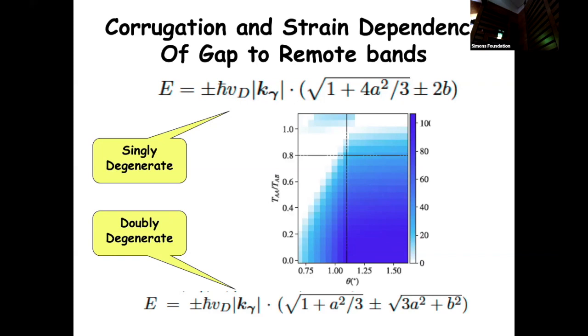And that changes the shape of the periodic potential, or the periodic tunneling between the two layers, which defines the Moiré pattern. And in particular, there are two parameters that appear in most models, and A and B in this expression are dimensionless versions of these two parameters. They're just tunneling between the same sublattice, AA tunneling, and tunneling between different sublattices, AB tunneling.